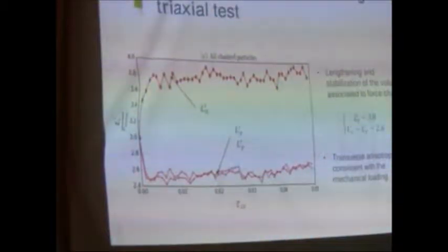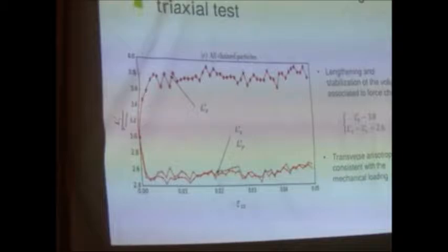So if we reconsider our initial sample with respect to this length scale, we have a sample that is approximately 30 times bigger in every direction than this typical length scale. So a posteriori we can say that our sample was sufficient to represent a representative elementary volume and justify a priori the approach I've carried out.